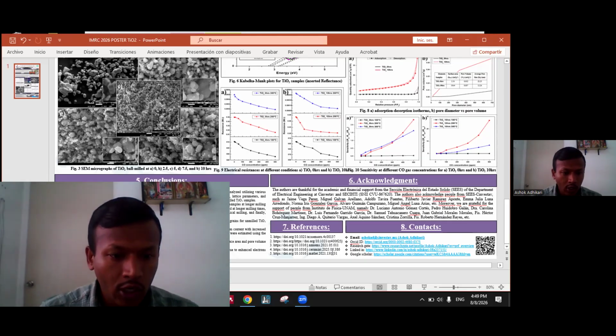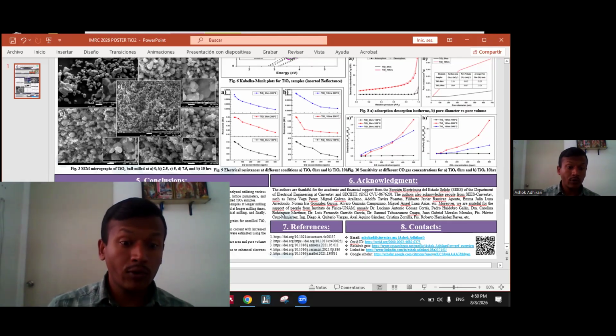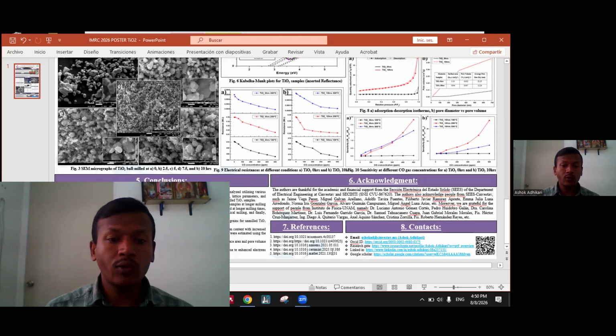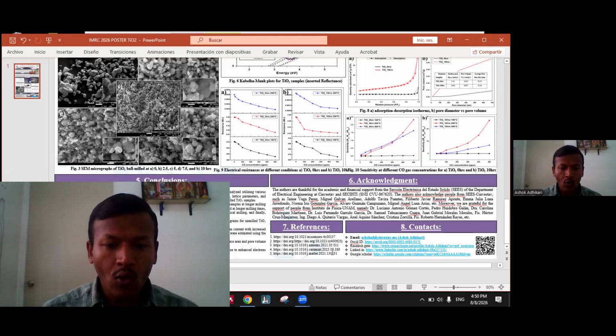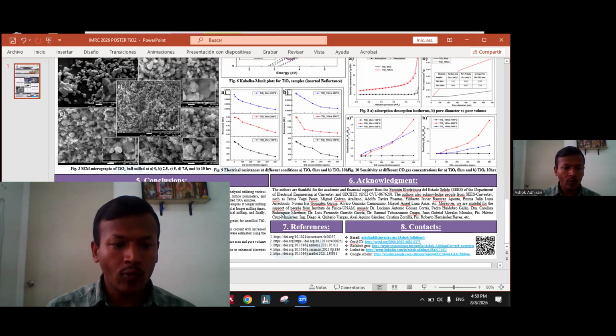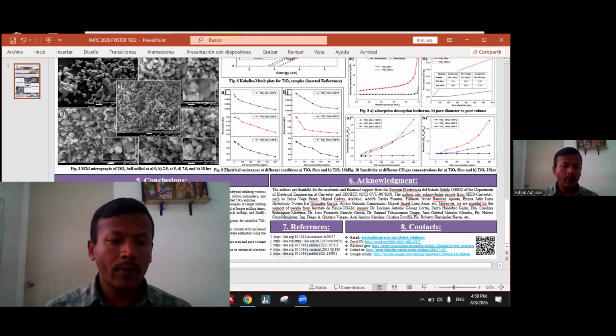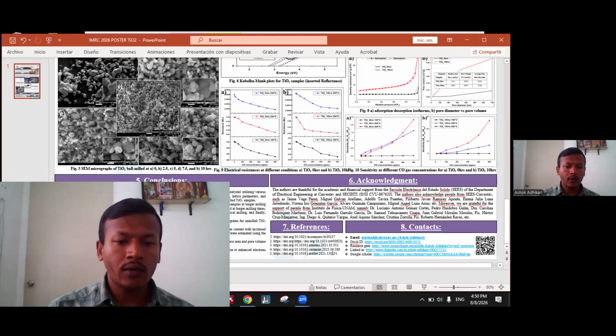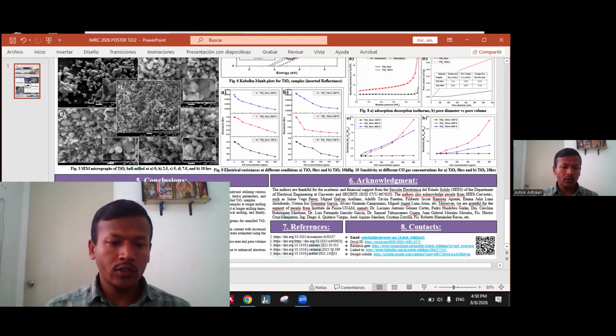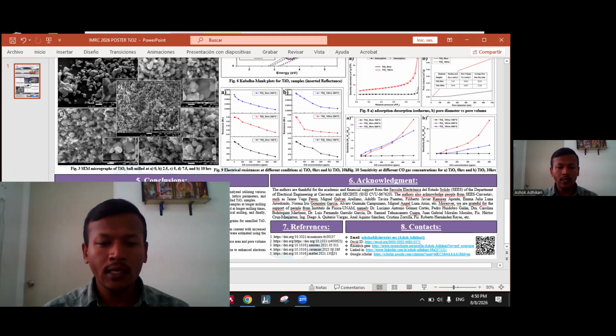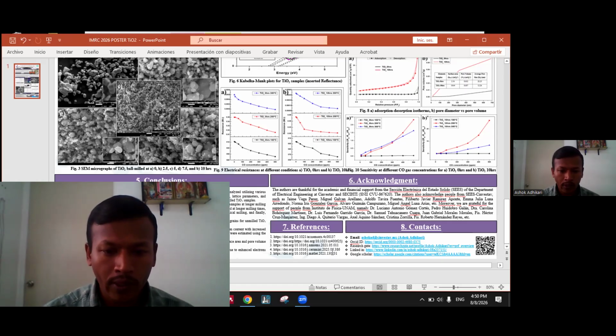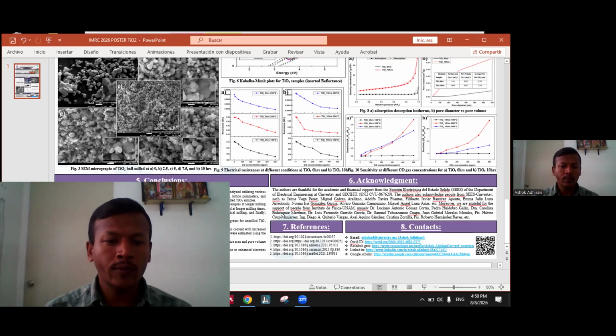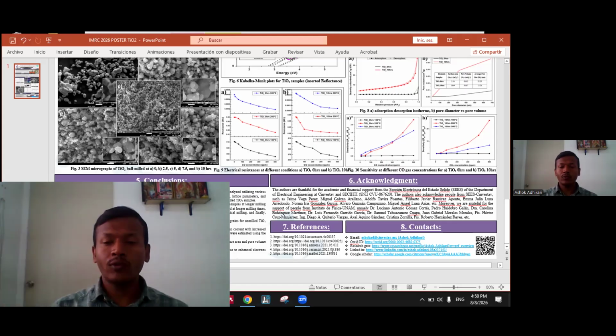BET analysis verifies mesoporous TiO2 particles with a plate-like structure with wedge-shaped pores, where the surface area and pore volume for the milled samples are comparatively larger than those of the unmilled samples. It is noticed that the surface electrical resistance values decreased with an increase in operating temperature due to enhanced electron excitation into the conduction band, and with gas concentration by releasing electrons during surface reaction with CO gas.